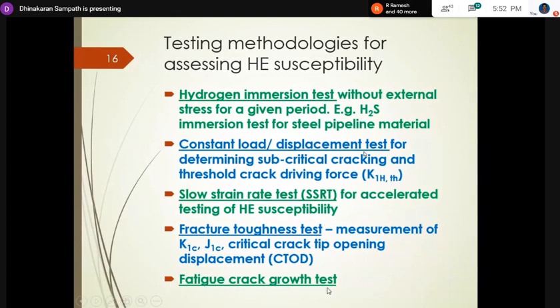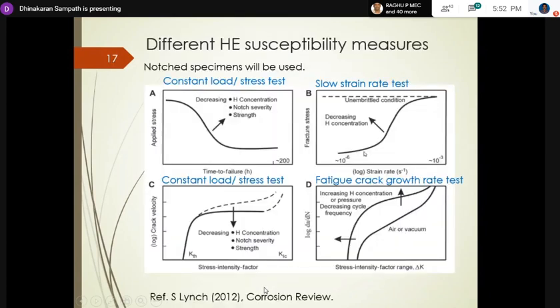And then the last one, if the component undergoes fatigue, cyclic loading in hydrogen, then fatigue crack growth is important. I'm going to show some susceptibility measures. So in different tests, what kind of information we get. Most often in hydrogen embrittlement susceptibility evaluation, they use notched specimens, because the key thing is that hydrogen gets accumulated at the crack tip, and that sustains crack growth.